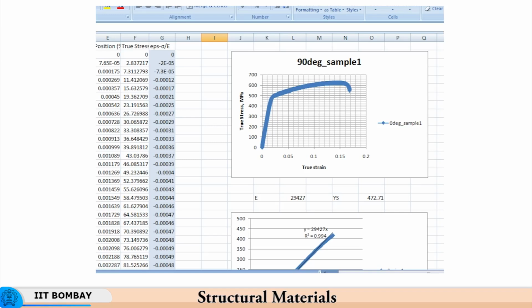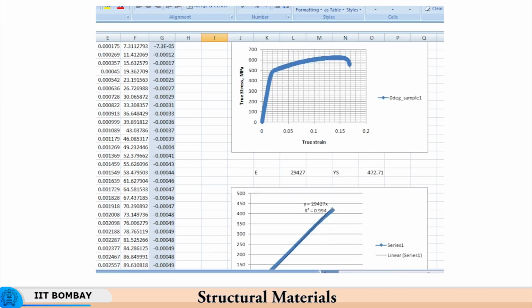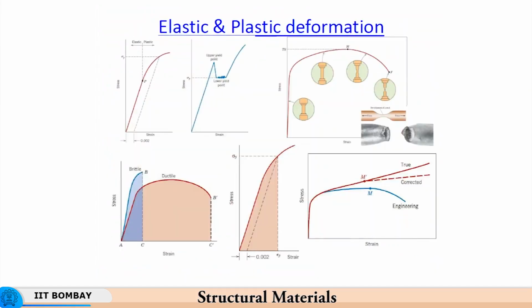Therefore, we plot a parameter of epsilon minus sigma by E. In terms of the slide which I had shown you, the recoverable elastic deformation, we are trying to find this. Epsilon is from here to there, and sigma by E is from here to there. So, what we are trying to do is subtract sigma by E, which is the recovered elastic strain, from the overall strain. The overall strain is epsilon and sigma by E is the recoverable elastic strain, and what is left behind should be 0.2%, 0.002.